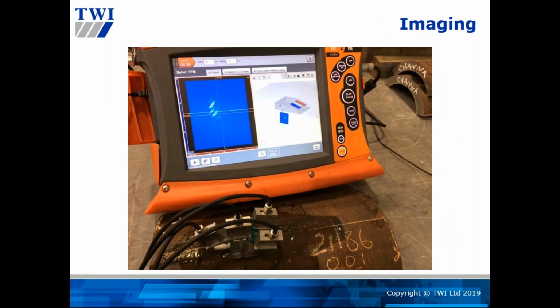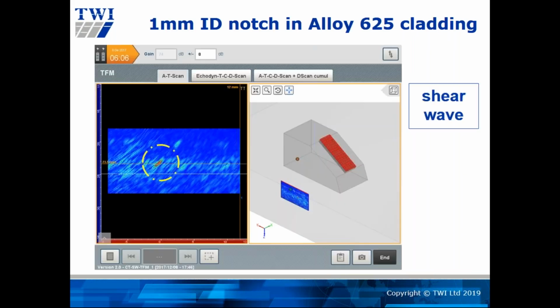Here is one of the ways of using the probes, using an imaging technique called FMC/TFM. Here we have an instrument that is operating the probe, and there you can see the signal from a specific flaw in the pipeline. So when you look at the cladding with the shear wave, what you see is that there's a lot of backscattered noise that is generated.